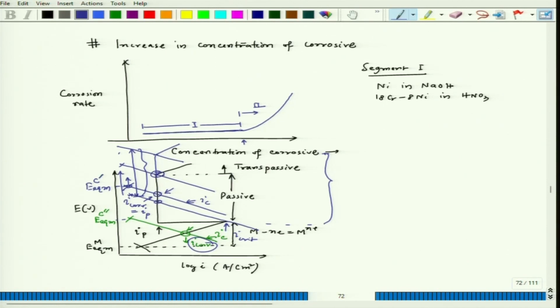This particular flat zone is observed in the case of nickel; two such examples are nickel in NaOH or 18-8 chromium steel in HNO3. So, there, over a wide range of concentration, the material can remain in the passive zone. That is why you have a constant current density equal to I passive, and the corrosion rate also remains almost constant.